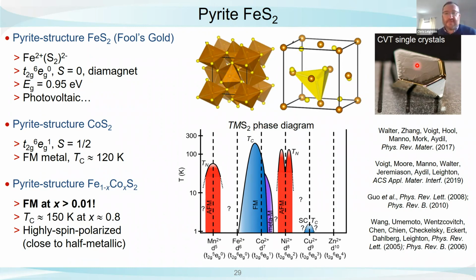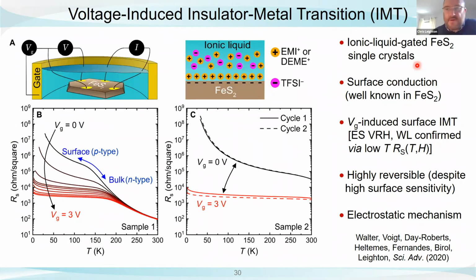Okay. So this is what we tried to do. We did it in a fairly crude way. This is a bulk single crystal of iron sulfide. It's in an ionic liquid this time as the gating medium. We're applying only positive voltages. We're trying to induce electrons in the iron sulfide.